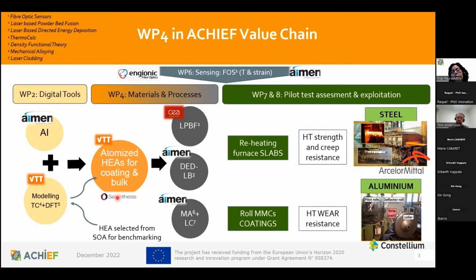Once we have the powder, we move to the additive manufacturing processes. So we have here CEA that is in charge of the laser PBF process, AIMEN that is in charge of the DED laser-based, but also the laser cladding process, together with the mixing of the high entropy alloys with some reinforcement in order to get these high entropy alloys with some kinds of particles inside in order to increase the wear resistance.